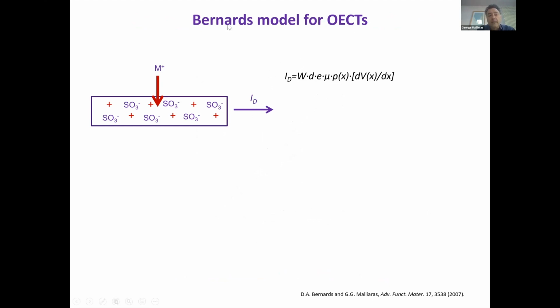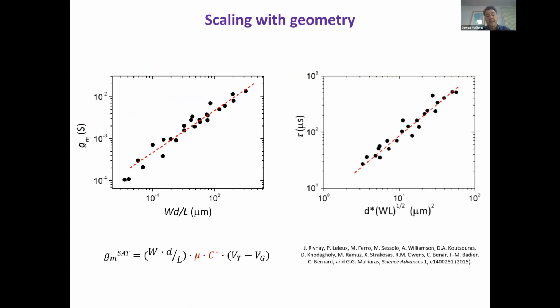And we built a model, which is called the Bernards model, that explains the behavior of this. I'm not going to go through the details, but it explains how the electrical characteristics of this behave based on very simple processes where ions from the electrolyte go into the film, and then a hole gets extracted and doesn't get replenished, so the material gets de-doped. You can write very simple equations, integrate them, and then you get the behavior of the system. For example, the transconductance, which characterizes the amplification that you get in this transistor. You find that it scales with the thickness of the film, which is unusual for a transistor. It's a characteristic of this volumetric capacitance of PEDOT.